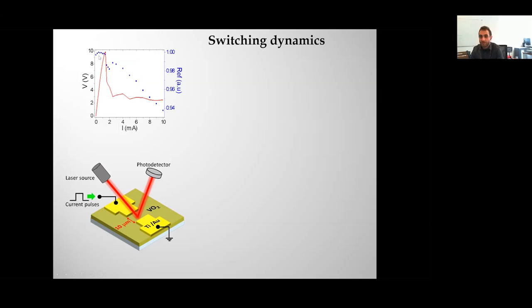So here, this is as a function of current, what is the voltage? This is the red line. You can see resistive switching and the reflectivity. And you can see that indeed, as soon as you induce the transition, you have a jump down in the reflectivity that keeps going down as you increase the current and your filament becomes wider. So it's a very good proxy to measure what is the amount of metallic domains that you have.